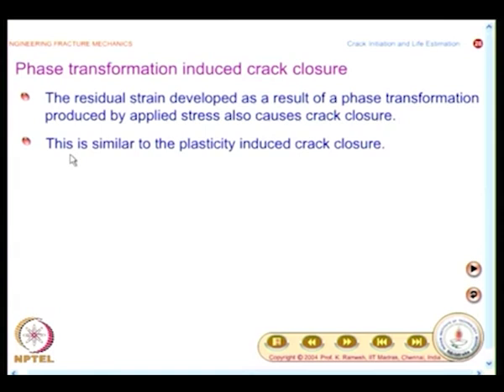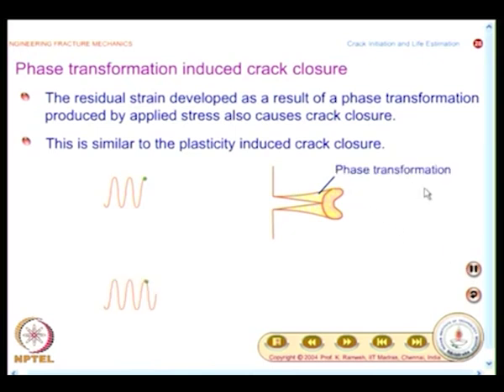Instead of the plastic wake, here it would all be dictated by the phase transformation, otherwise there is a comparison between the two, and that is what is mentioned here. This is similar to the plasticity induced crack closure. Here again you look at it after a few cycles at the peak load. At the peak load the crack is open. Just to distinguish it from plastic wake, here the shading is different, but these pictures are essentially the same, and this is because of phase transformation.